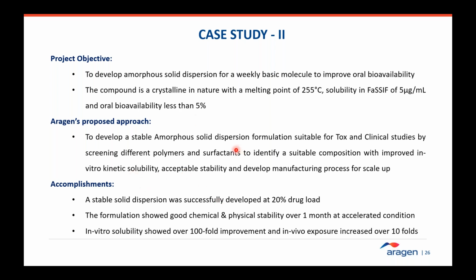We conduct the same screening, but based on the molecule, different polymers, surfactants and drug load are selected. So at this stage, we can see that we typically optimize all the formulations at 20% drug load at the tox phase, and then as the clinical doses come down, we optimize this further to improve the drug load up to 40% at the later phase.